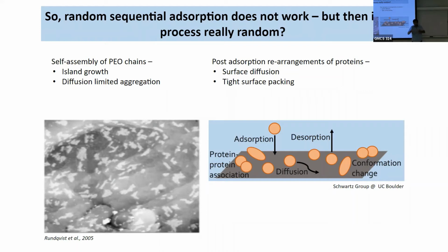Okay, so the polymers themselves end up clustering together, especially in a few of the methods where you have this formation of self-assembled monolayers. When you have these self-assembled monolayers, they sort of start clumping together. And so if you look at the distribution of the polymers on the surface, you have them clumping together and forming islands. Okay? And even proteins, when they sit on the surface, they don't just sit and stay steady. They'll sort of nudge each other around, and there is another one that's trying to come in. They'll nudge each other around and maybe create spots and spaces, so they can actually tightly fit.